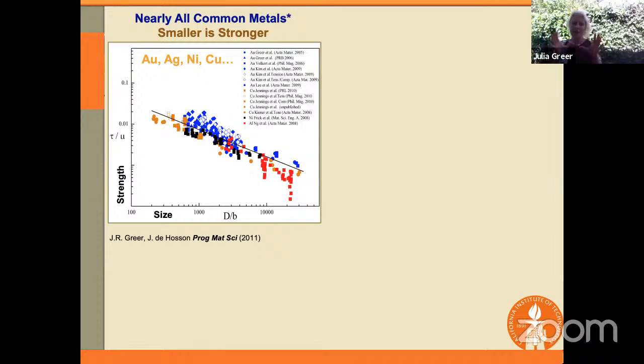And we'll look at them in their single crystalline form so that there are no grain boundaries. There might be defects, but there are no grain boundaries. What emerges is this very, very strong strengthening. Now, again, this is a log-log plot. In a log-log plot, of course, a linear slope indicates a power law. So this is very powerful strengthening.